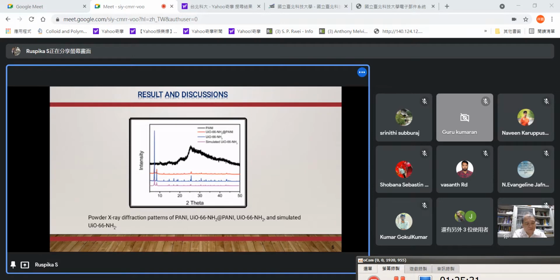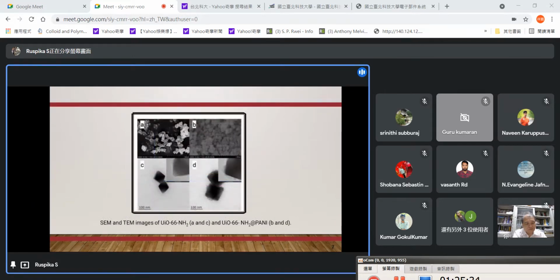And this is the SEM and TEM images of UiO-66-NH2. It is shown that it has more regular facet surfaces than UiO-66-NH2 PANI. Both of them have discernible and better dispersion, which can facilitate the formation of a robust homogeneous film for the construction of an electrochemical sensor. The TEM images confirm the octahedral cubic intergrown crystals and clearly reveal the core shell morphology of the composite.